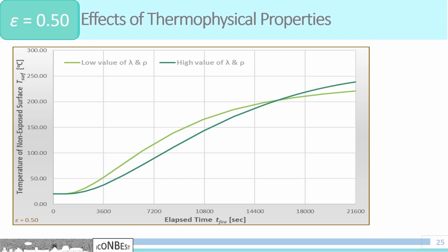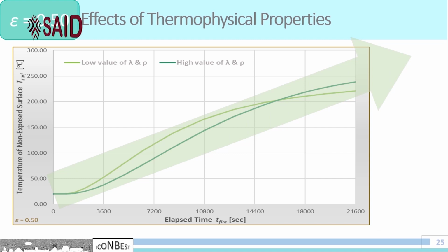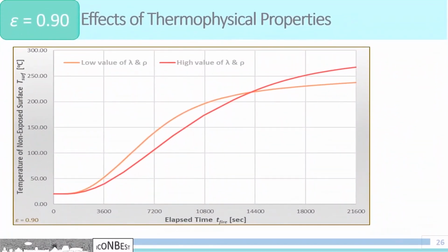Nevertheless, a careful examination of the following findings of this work indicate that the thermophysical properties of a clay material, such as the thermal conductivity and the density, can shift the ranking of the optimal masonry wall configurations subjected to fire at a certain time point. In this regard, the green semi-transparent band reveals this aspect for an emissivity value equal to 0.5. A similar trend is also shown for an emissivity value equal to 0.9. In that respect, the orange semi-transparent band corresponds to the critical tipping point of this heat flow evolution. This implies that the thermophysical properties of a clay material of hollow bricks should be emphasized at the very early stages of building design and modeling.